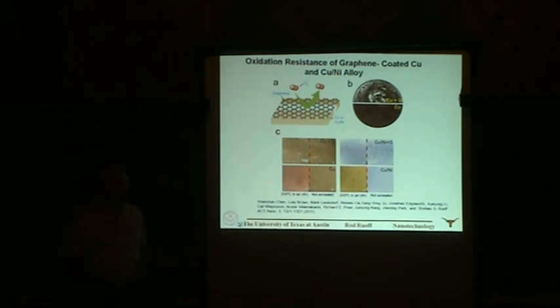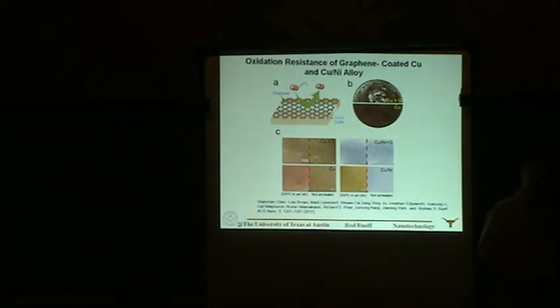So we were trying to understand the kinetics of growth. And in our experiment, unlike the surface scientists, we don't have in situ methods of observing the growth. So all we can do in these sorts of thermal CVD experiments is grow for a certain amount of time and then stop, and take it out and look at SEM and so on. And we see those sorts of flakes. Or we can try to stop very quickly and the flakes will be smaller, which we call islands.